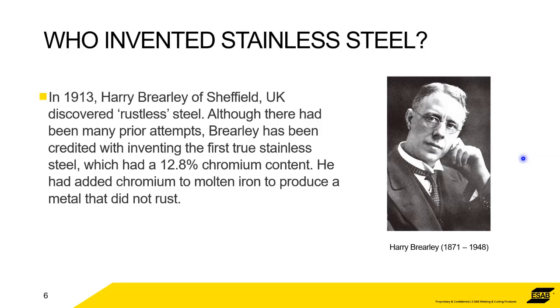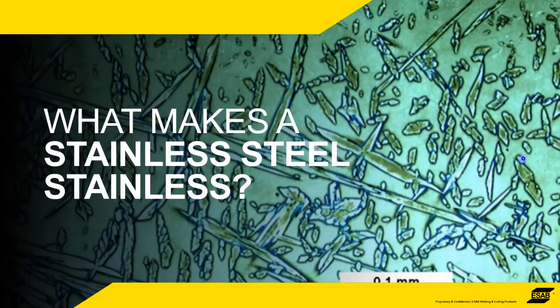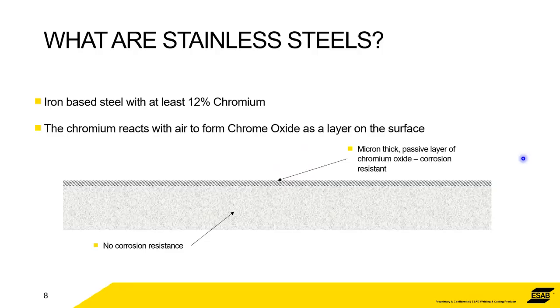So what is it about this 12% chromium in the steel that makes it stainless? Well, there's almost like an excess of chromium in there. You've got more than 12% in the base metal, and the surface of that will react with air, and the oxygen in it will turn chromium into chromium oxide. Chromium oxide is very inert. It's very passive, and it's very corrosion resistant. So if you have a layer of chromium oxide over a base metal, then it will stop it from rusting. It will stop any kind of corrosion from happening.